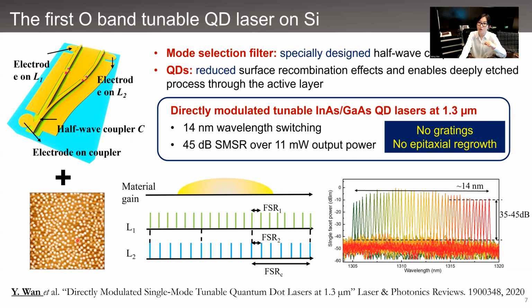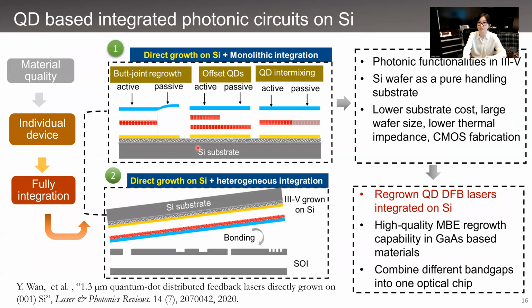So with this simple and integrable device structure, without using any grating lithography or regrowth process, we demonstrate the first tunable single wavelength quantum dot laser, where we have these two Fabry-Perot cavities with slightly different lengths to shape the Vernier spectrum for wavelength tuning. And we achieve this 14 nanometer wavelength tuning with up to 45 dB side mode suppression ratio. In addition to the improvement of material quality and individual quantum dot device performance, a lot of efforts are also needed to form fully integrated photonic circuits.